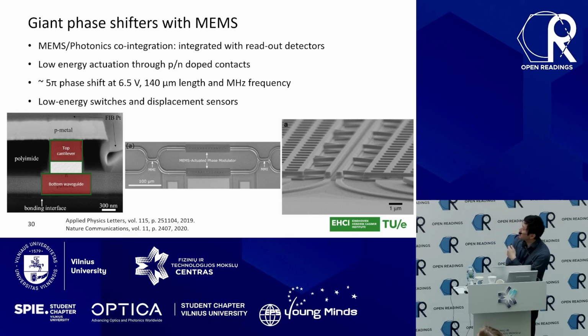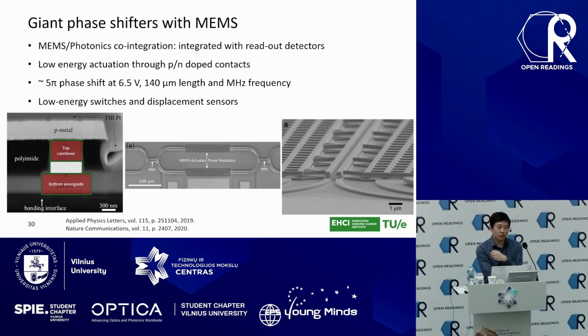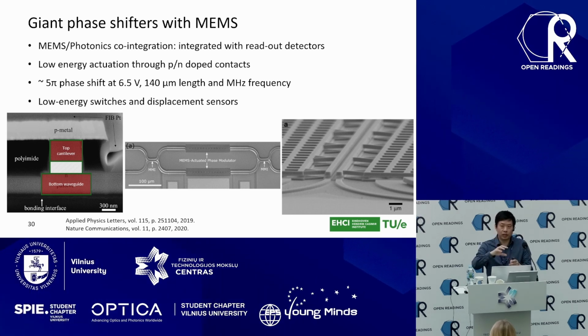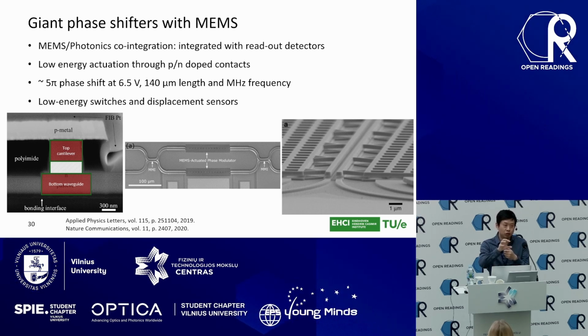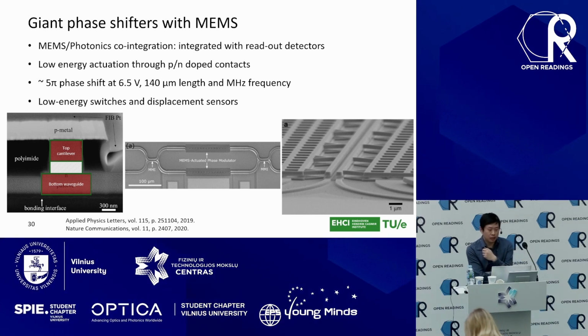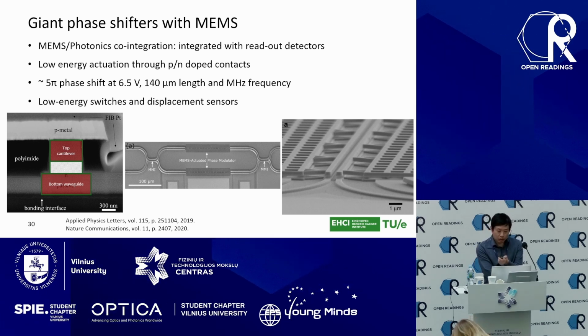Our game doesn't stop. We can also play with some exotic stuff. We're inspired by the layer stack of our laser diode structure, because we have an indium phosphide-based cladding, P and N side, and in the middle we have a ternary or quaternary-based active region. By selective processing, you can actually remove the center active region and make the top cladding suspended. So then you create a MEMS, or people call it NEMS, right? Nano mechanical system.